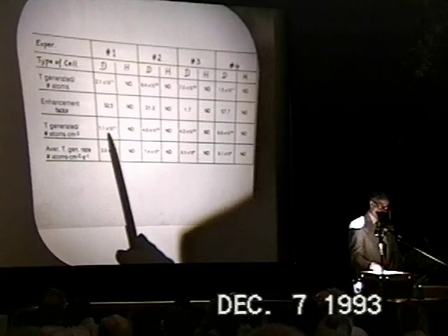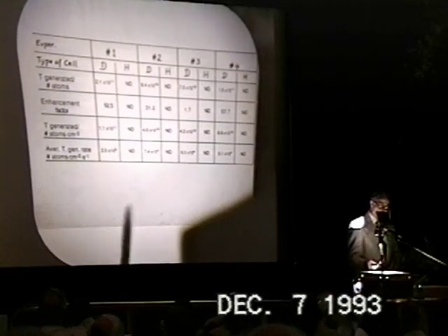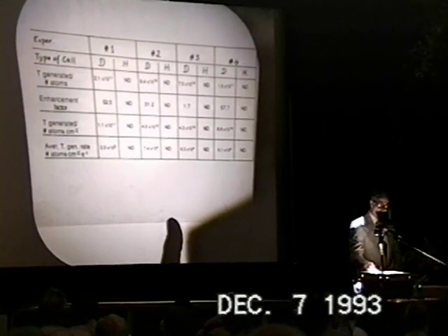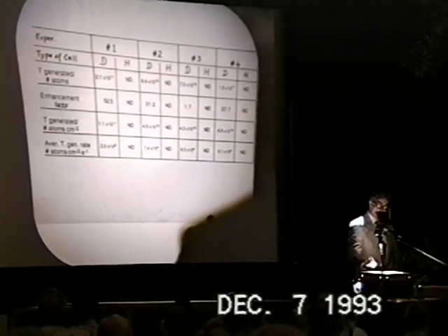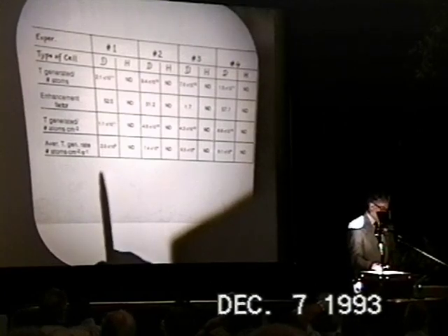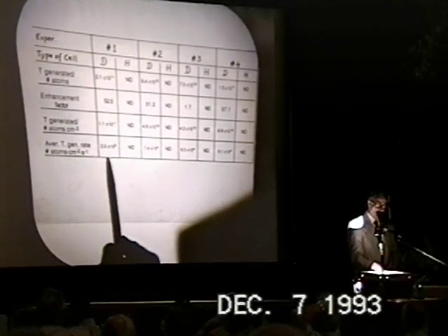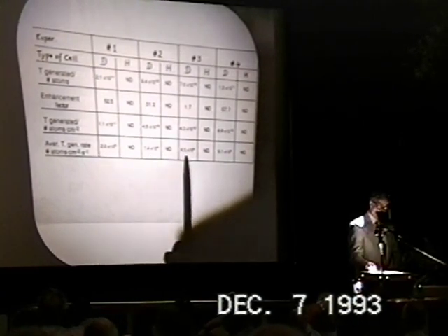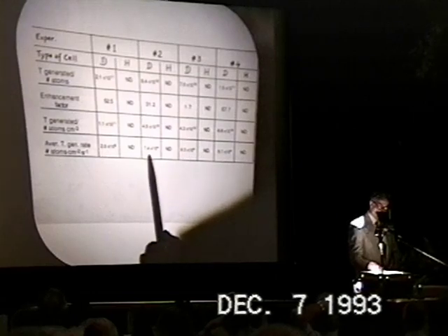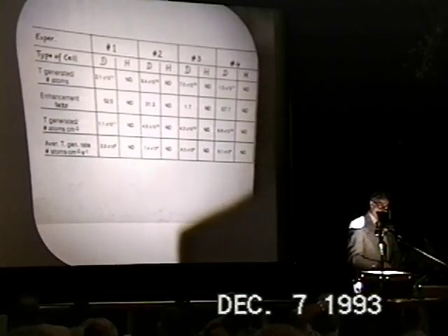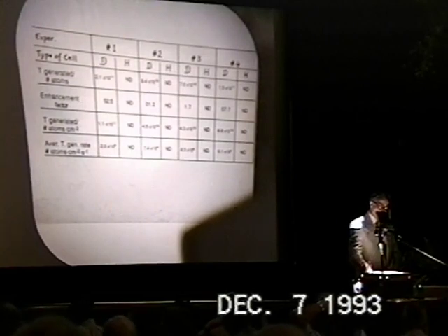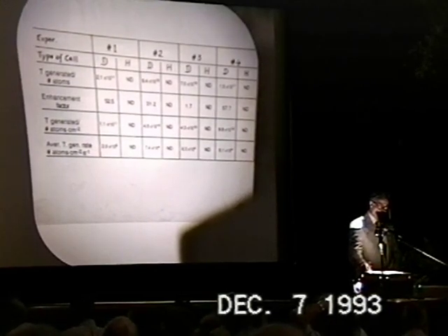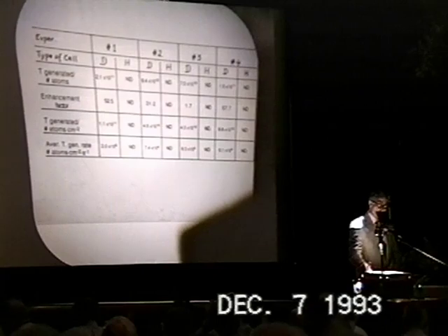in the other cases. And here finally is the average tritium generation rate, starting again to count at the time the palladium had reached a loading ratio of 0.8, and we notice once again that the average tritium generation rates are relatively uniform and are of the order of 10 to the 5th atoms per square centimeter per second, which then corresponds to about 0.1 micrograms.